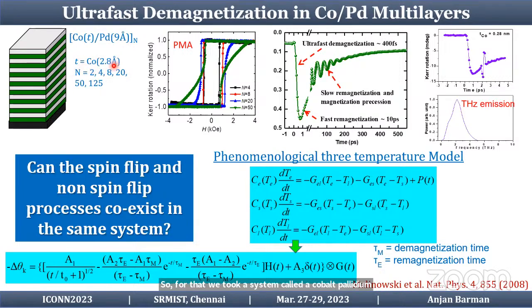Here, the thickness of the cobalt is 2.8 angstrom, whereas palladium is 9 angstrom, and we repeat the cobalt palladium bilayer from 2 to 125. As a result, the perpendicular anisotropy changes in the hysteresis loop. You can see it deviates from the square loop. As well, there is a variation in the overall thickness of the sample.